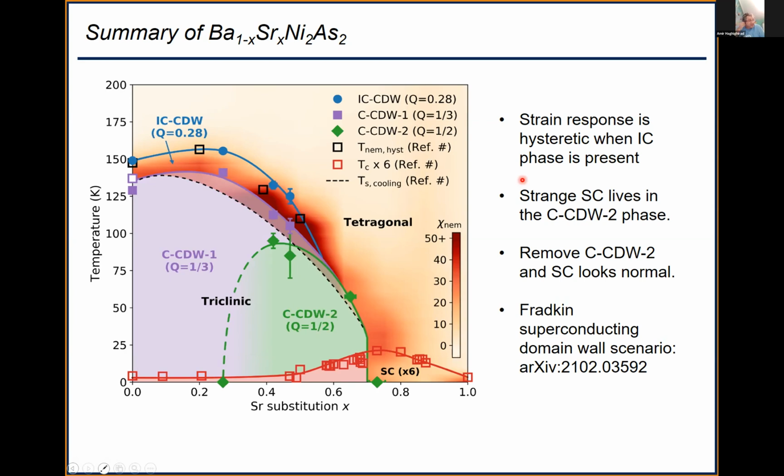So if we now say that this is crystallographically belonging to a tetragonal phase, I have a problem with that because, first of all, it is incommensurate. And actually, if it would be the 1/3 reflection, I could do something in defining a different cell. But in this case, how could you actually define a cell when you have an incommensurate wave vector? So already, if you say it's incommensurate in a tetragonal phase, I would say that's a charge density wave, unless you come up with something else.